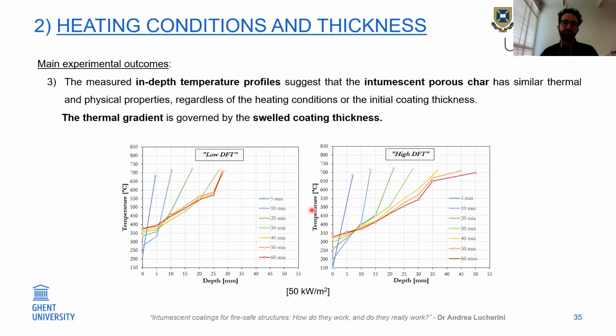Then another conclusion from the previous experimental campaign that I showed you earlier is that the measured in-depth profiles suggest that intumescent porous chars have similar thermal and physical properties, regardless of the heating conditions and the initial coating thickness. In particular, you can see here the depth of the coating and the temperature, and then the evolution at different times. So you can see that here, at depth 0 of the coating, so the steel substrate, the coating has a very similar range when the swelling is not happening. When the swelling is happening, the coating starts swelling and the gradient is stretched across the thickness of the coating.